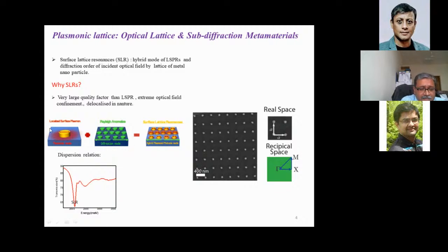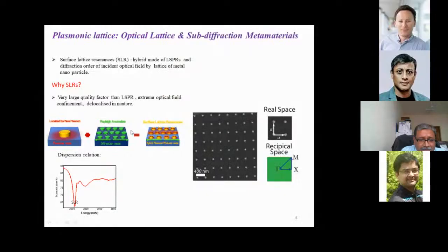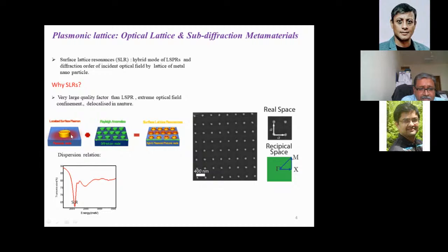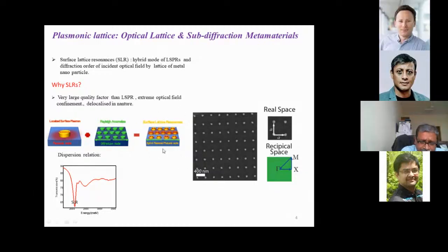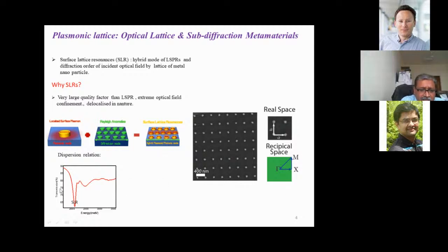The individual plasmon mode and the field is well known, I guess, to the audience, so I don't have to introduce it. But when you create this array and they are coupled, then apart from the localized mode, you also create what is called the diffraction mode or the surface lattice resonance. If you do a transmission measurement, you can see this very sharp resonance. The typical plasmon resonance would be broader, but the lattice resonance is very sharp due to this strong coupling. You can vary the lattice spacing here, typically of the order of 400 nanometers, and you can go even higher to larger separation, basically shifting the position of this resonance to a larger wavelength as you increase the separation for the lattice.